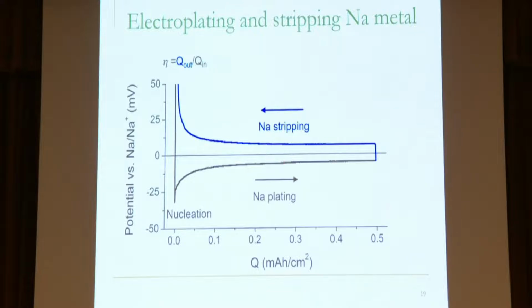We stop the current here, and we switch the polarity, right? So we turn the current the other way. We turn it positive if we're making it negative in the beginning. And then it slowly strips off, right? But it never comes back to where it originally was. You see that there's a little gap between these two curves. And that gap comes from the second law of thermodynamics. Second law of thermodynamics tells you that you never win. You always lose. And that little gap tells us how much we lose, and specifically how much charge we lose. That gives us an indication of the charge efficiency.